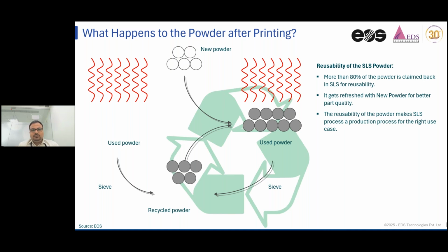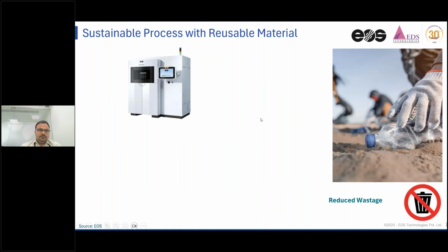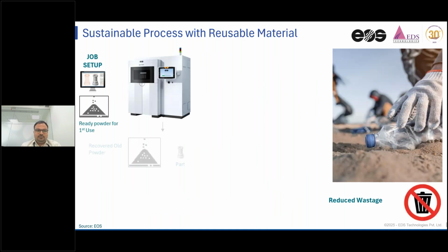So right now, with a few of our selective materials, we are able to reclaim 80%, and if we are printing 15 to 20% of the volume out of the quantity that we have taken, we end up with almost negligible wastage in the process. Since there is very minimum wastage, this process becomes very sustainable once that part is taken out.